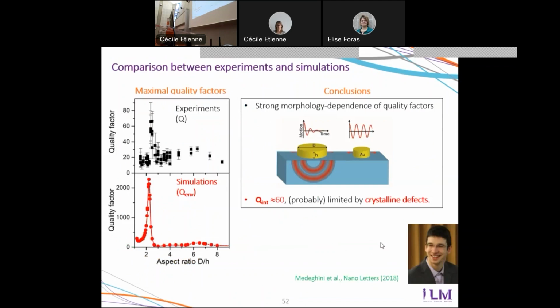So we compare here quality factors in experiments and in simulation. What you see is that usually the quality factors are low, of the order of 20 here, also of the order of 20 here. But for specific aspect ratios, near 2 or 2.5, we have in both experiments and simulations a strong enhancement of vibrational quality factors. So it means that for specific shapes of the nanodisk, we prevent emission of acoustic waves in the substrate. We block this emission, and the vibrational damping of these objects just comes from internal effects.